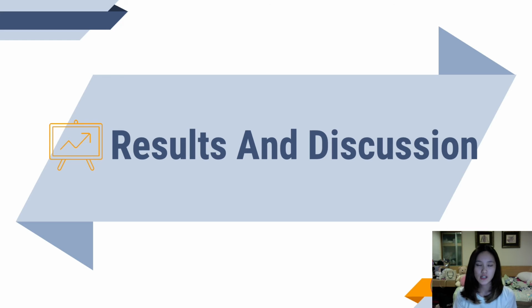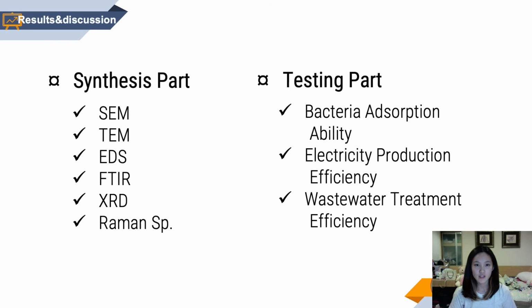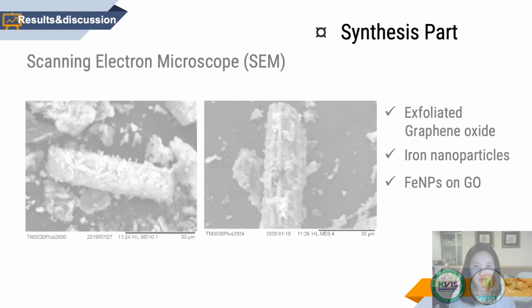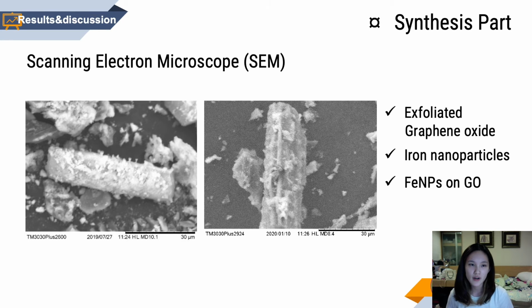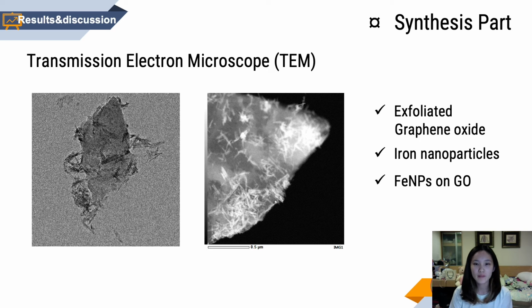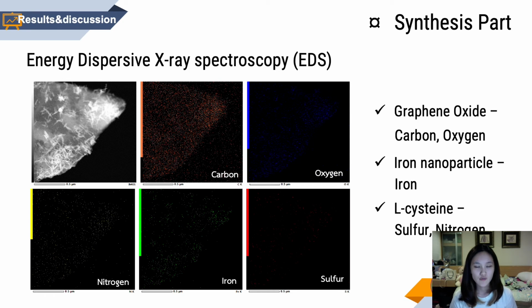Next are the results and discussion. The results are in two parts, which are the synthesis part, with many characterizations, and the testing part, to test the ability of the MFC using our sample. For the synthesis part, first, SEM can confirm that there are graphene oxide sheets and also iron nanoparticles on graphene oxide. TEM also confirmed both of them. From the EDS result, we can see that there are carbon and oxygen which come from graphene oxide, nitrogen and sulfur from L-cysteine, and iron from iron nanoparticles. All the elements are dispersed all over the graphene oxide sheet.